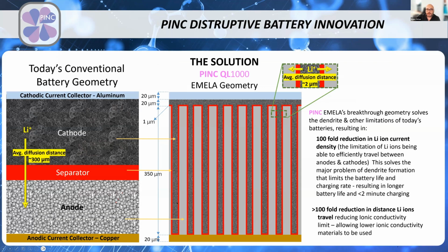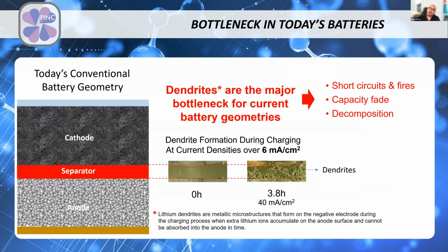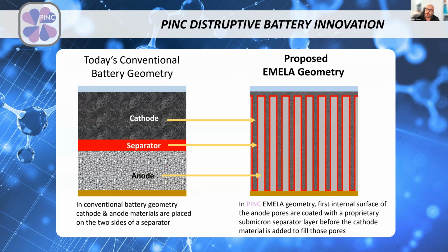This has two main benefits. One is again the surface area, and here I'll go back a few slides. What we are trying to improve is the centimeter square. If you improve the centimeter square, you can reduce the ion current density quite a bit, so then you can stay well below the dendritic formation threshold. That gives the opportunity to charge much faster. We are talking about hundreds of times faster.